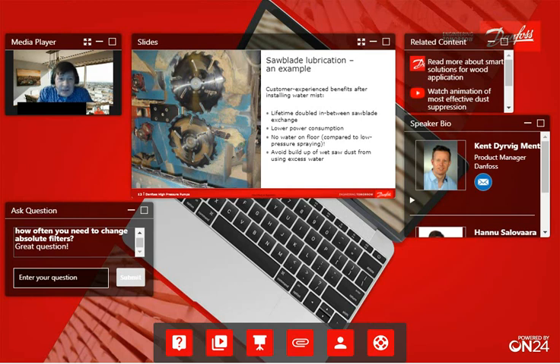It also means that the lifetime is longer, because the blades stay clean a longer time, and there is lower power consumption. You can see it because you are using big motors. We haven't tested it in an official way, but we know that it lowers the power consumption. Also, there's no water on the floor, no damping problems or flooding problems in the basement of the saw machine. So if you are placing the right size of nozzles, you can't even see that there's a water spraying system inside the saw machine. But results are excellent. You can jump to the next one.